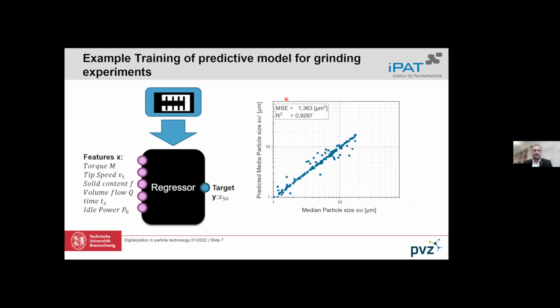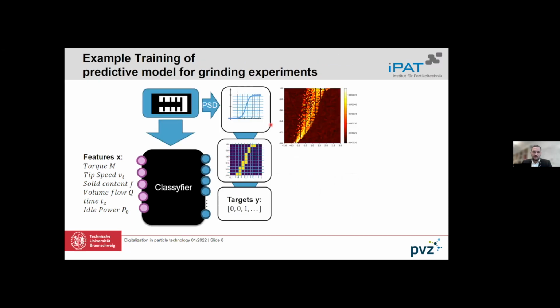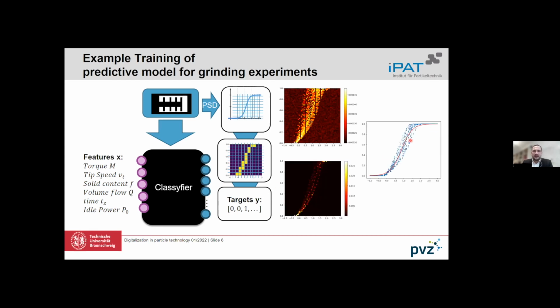The easiest way to use a data-driven model is to just use an artificial neural network for a grinding process within such a stirred media mill, and then feed in all process and formulation parameters and take a look at, for example, the median particle size. And on the right side, you see the prediction versus the measurement, which matches quite well. And if you take a look a little bit further, you can even go to particle size distributions with the same number of measurements. Here we are talking about 10 experiments and 10 particle size measurements per experiment. And at the end, you get a measured particle size distribution and a simulated particle size distribution. And again, it matches well, which shows the power of these data-driven methods.